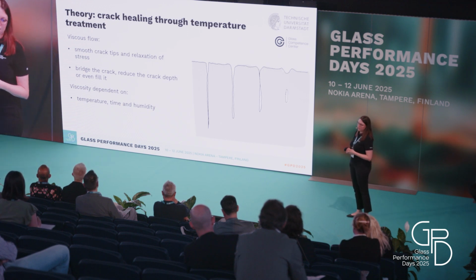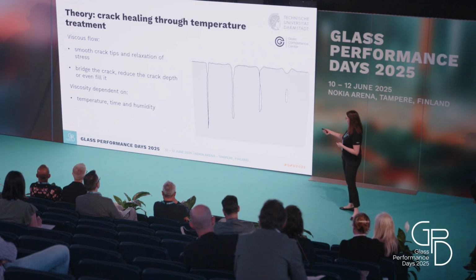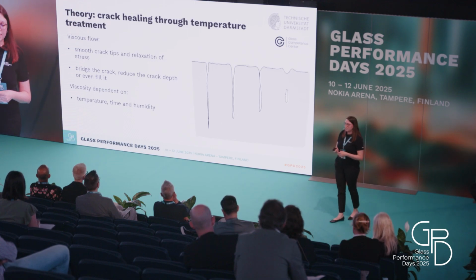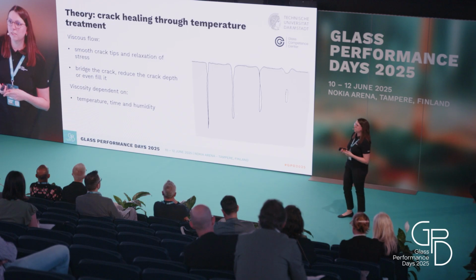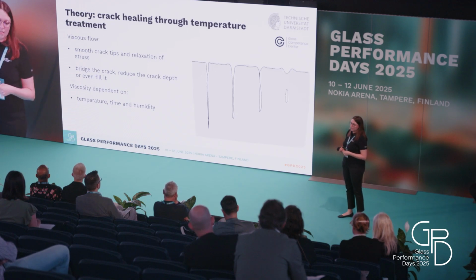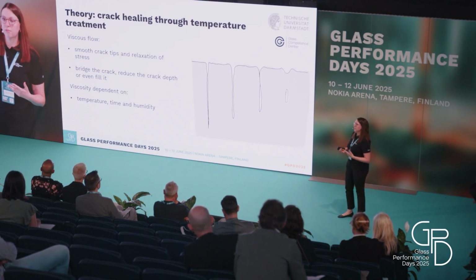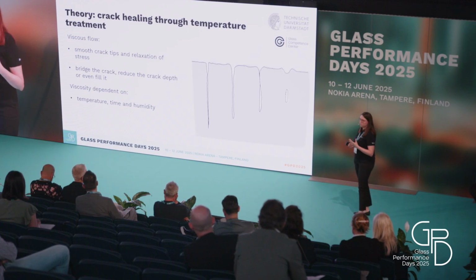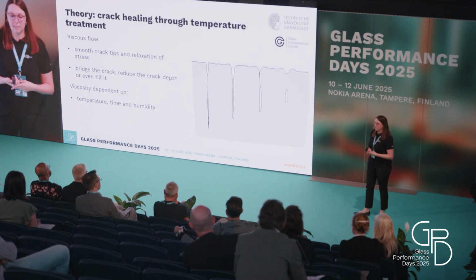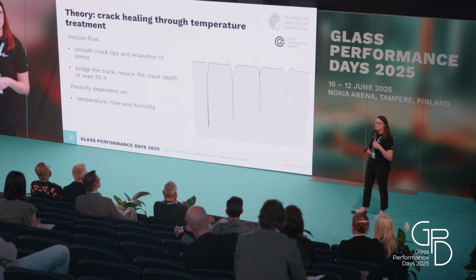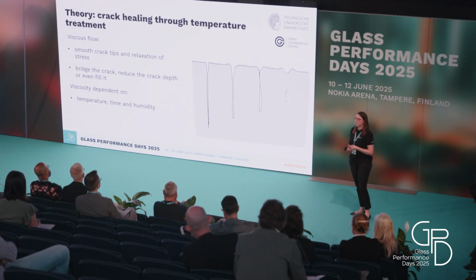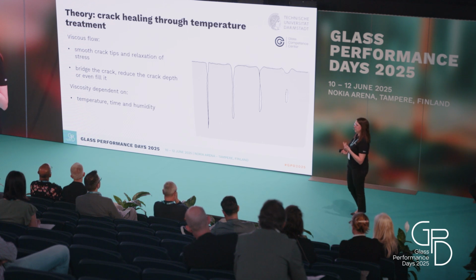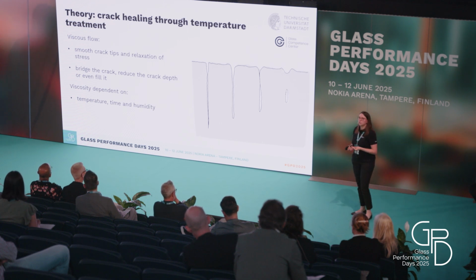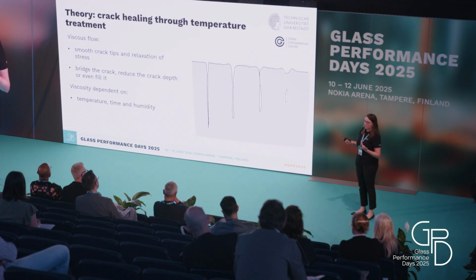This means that a sharp crack, as shown in the first picture, can smoothen out and the stresses around the crack are relaxing. The viscous flow can bridge the crack, the depth of the crack can be reduced, or it can even be completely filled up. And viscosity is dependent on different parameters, for example temperature, time, and humidity. The higher the temperature, the higher the time, and the higher the humidity, the lower the viscosity, and hence we expect a higher viscous flow.